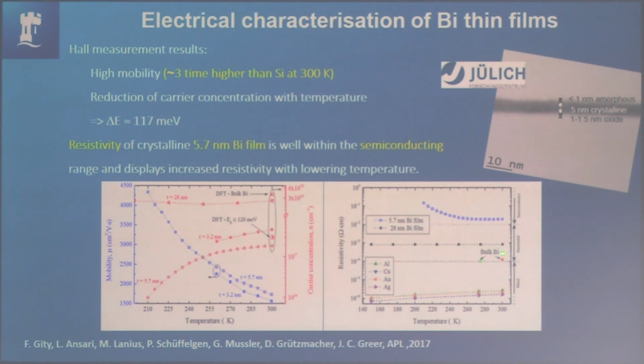This is also just showing you that bulk bismuth is much more conducting. These are typical metals down here. So experimentally, it does look like a semiconductor. Other people have reported similar measurements. So if you make it thin enough, it does look like it becomes semiconducting. But the great news for us is not so much the carrier concentration, but the mobilities.